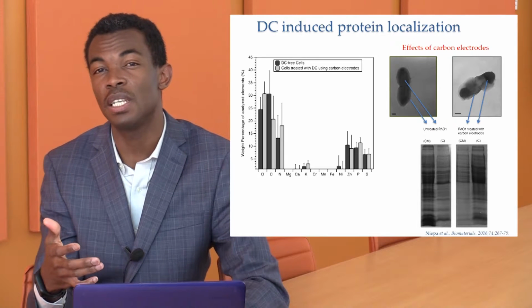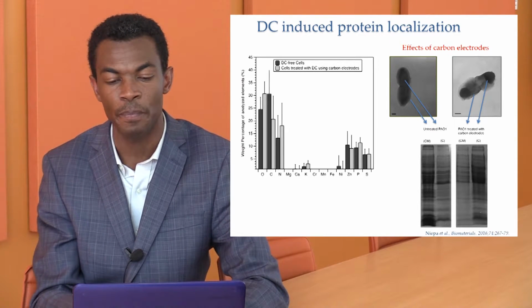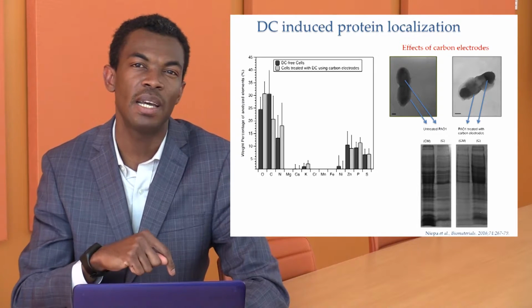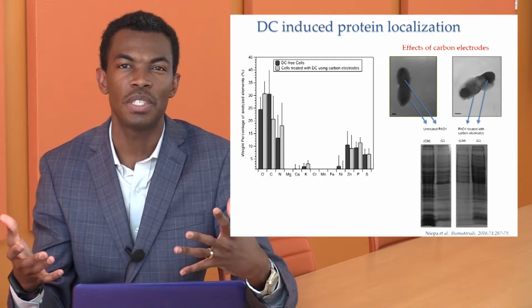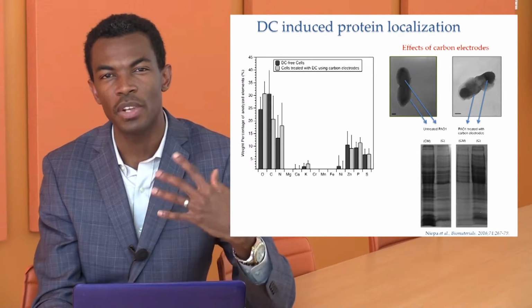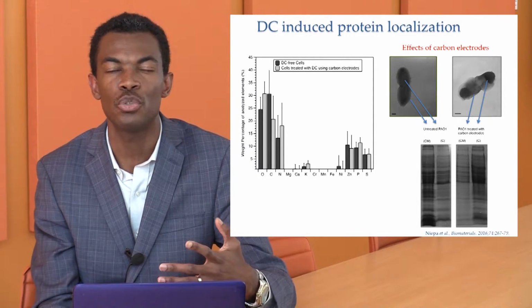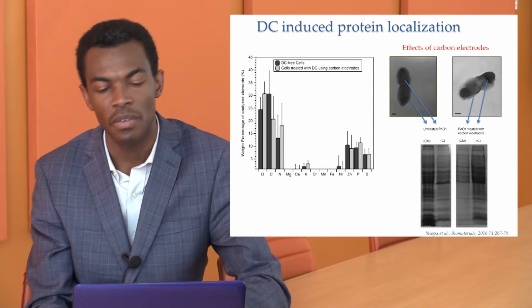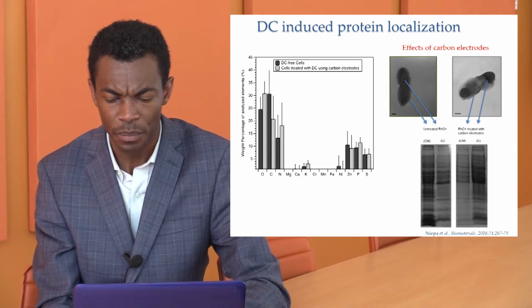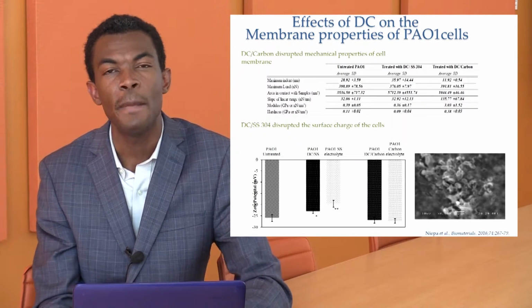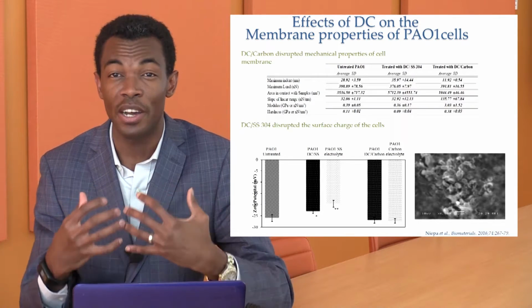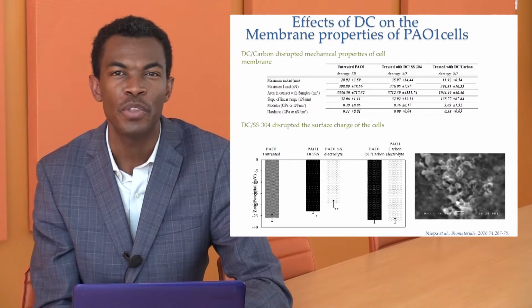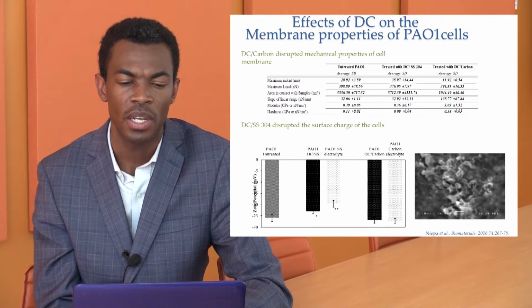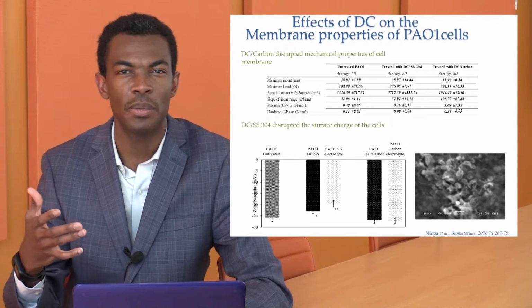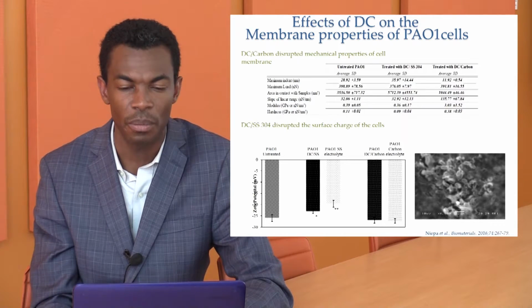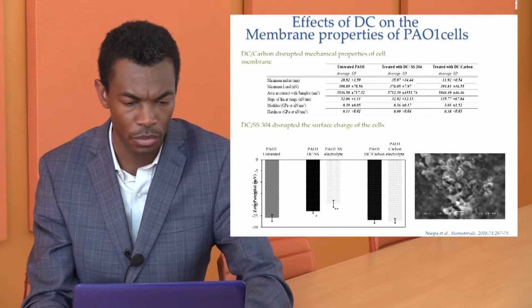But the cells treated with carbon electrode, as we can see, have more protein inside than protein on the cell membrane, meaning that again, the level of stress that we are applying by performing the DC treatment even changes the inner configuration of the cells. And it even goes further by making the cells even harder. So we did perform AFM to measure the stiffness of the cell membrane, and we realized that the cells treated with carbon electrode are even stiffer compared to the cells treated with stainless steel or the control cells.